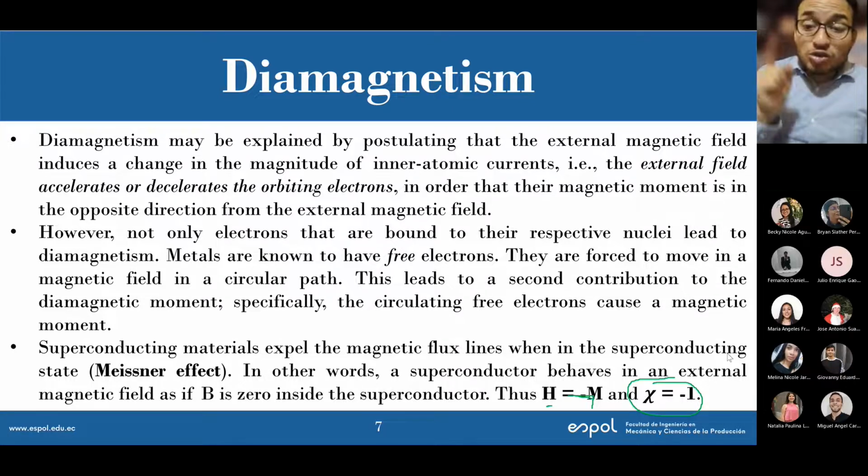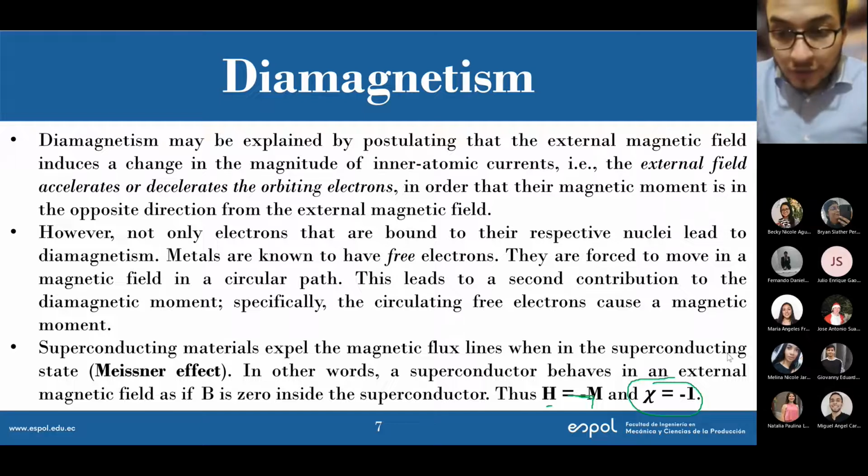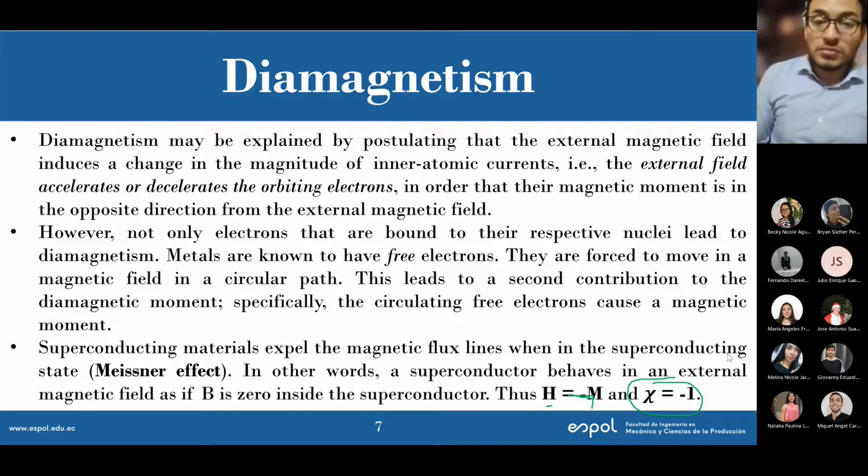And it's actually that strong diamagnetism of these superconducting materials that is used for frictionless bearings. That's why a lot of companies now are researching how they can improve just the mechanical properties, because the magnetic properties are already there in these materials.